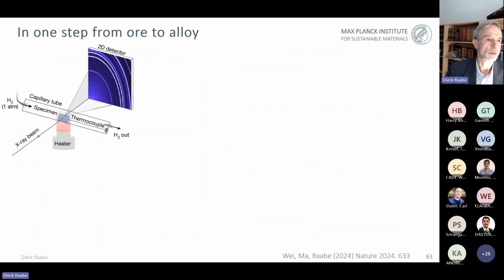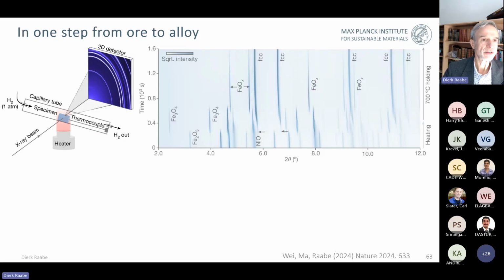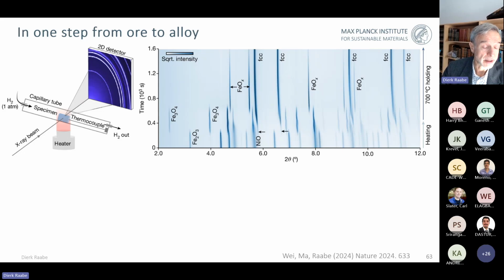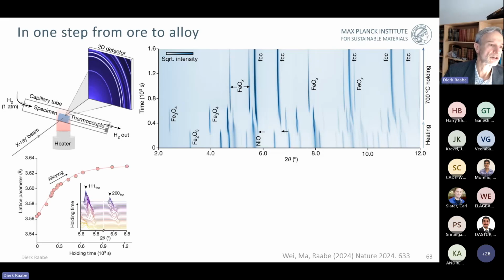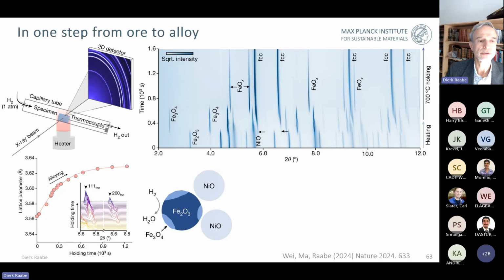What was interesting to see when you go into the detail here in the synchrotron analysis is that when you have only iron oxide and nickel oxide in the oven, it is not so that you reduce thermodynamically, of course, nickel oxide first into pure nickel, and then the iron oxide is waiting to be reduced as a second compound into pure iron. No, that's not happening. What is happening is that the iron oxide, once the nickel has been extracted from the nickel oxide, starts to partition into the freshly formed metal. That is seen in terms of the lattice parameter. Here from the synchrotron data, you can clearly see how the lattice parameters change. It means the nickel is directly forming an alloy while you still deal with iron oxide.